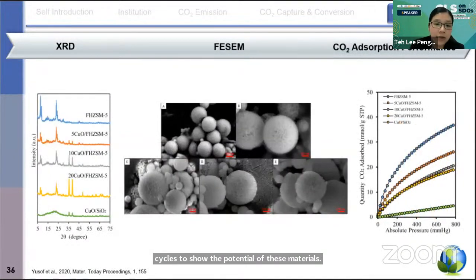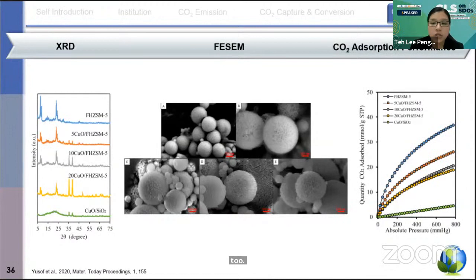We also studied the effect of copper oxide loaded on the fibrous HZSM-5 zeolite for CO2 capture. From this study, it demonstrates that the fibrous silica structures offer higher available space for CO2 absorption as compared to the commercial SiO2. So this can highlight the potential of the fibrous morphologies, and it is also very important in terms of the high surface area and porosity for enhancing CO2 physical absorption.